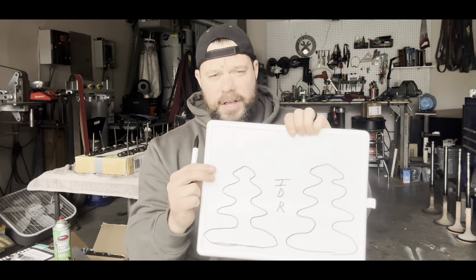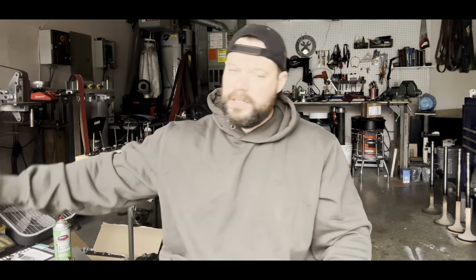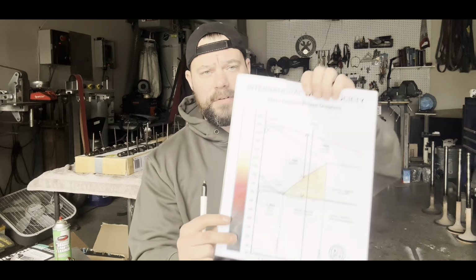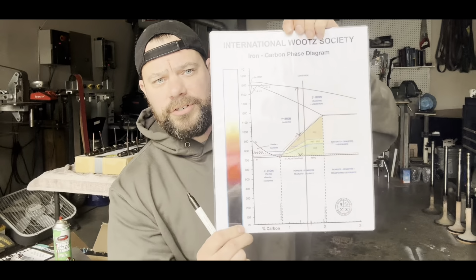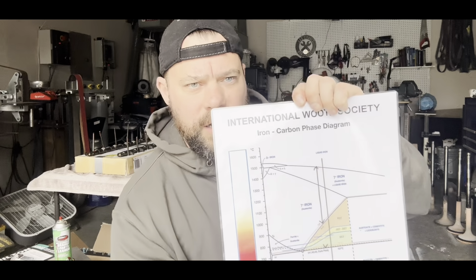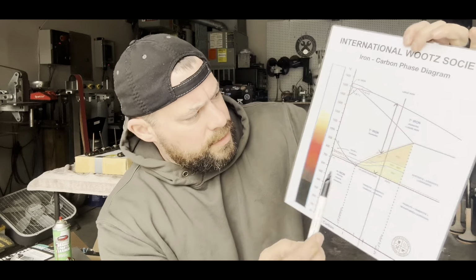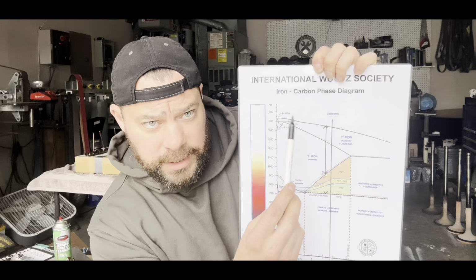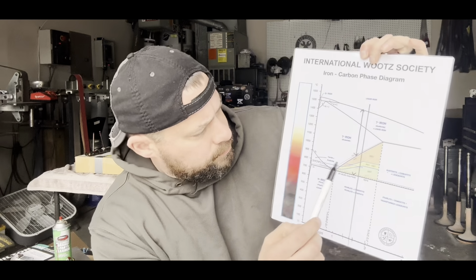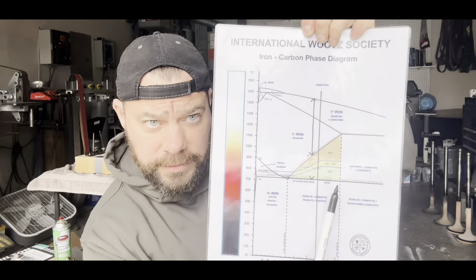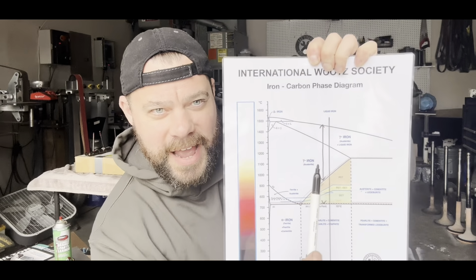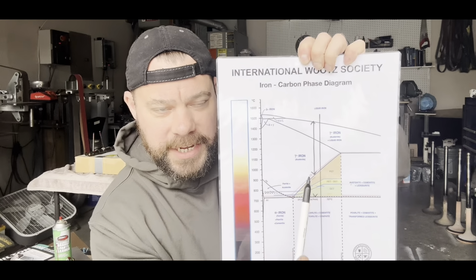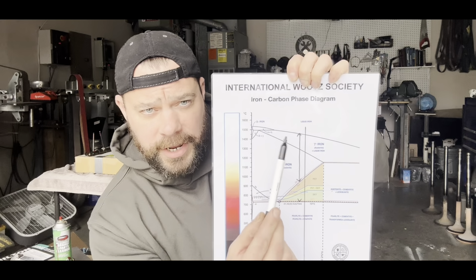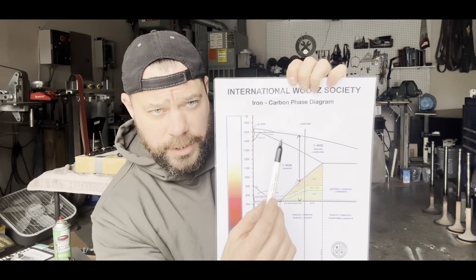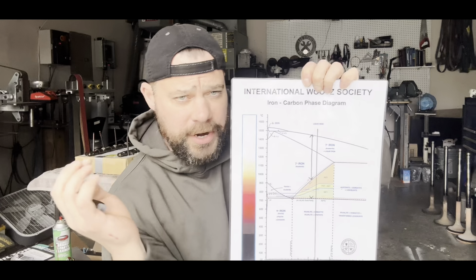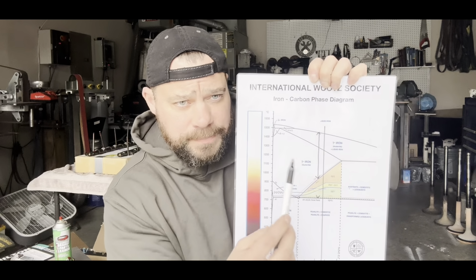I'll show you this on the iron carbon phase diagram here. I got this from the International Wootz Society. These are really great. But as your ingot starts to cool from liquid down to ACM, carbon diffusion is rapid. Your primary carbides are forming, and they're going to diffuse out to the grain boundaries.